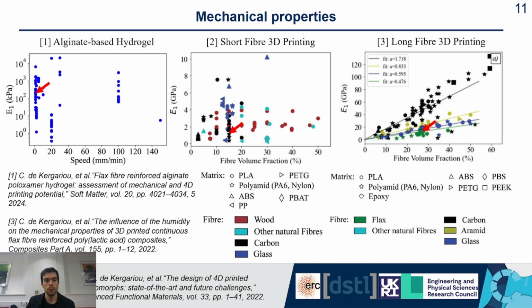You can see that for the first red arrow on the left, the alginate-based hydrogel has a stiffness of approximately 0.1 gigapascal. The short fiber 3D printed has about 1 gigapascal in stiffness, and the long fiber 3D printed has about 10 gigapascal in stiffness. And so basically, all these materials could be used for 4D printing.